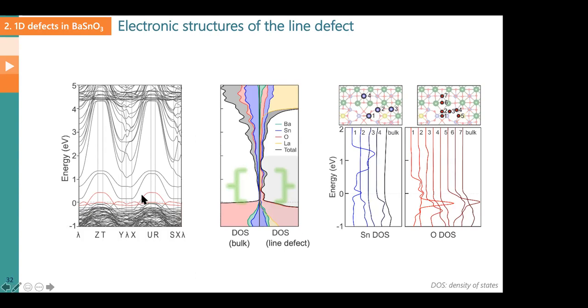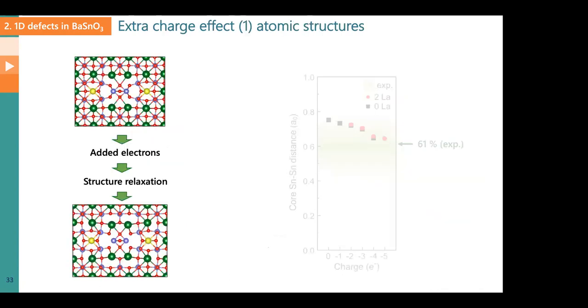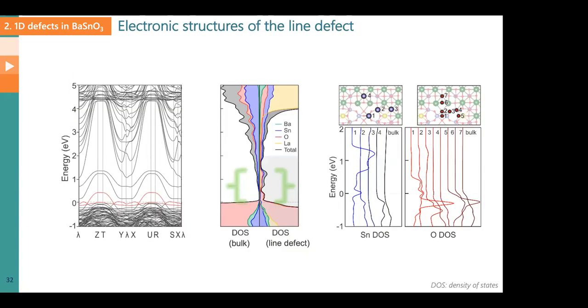But these red lines that come from a defect, from the barium and tin and oxygen, fill these prohibited energies. Now they're available there, allowing the defect to be metallic. So that's all good. We have a prediction that this defect should be metallic. We all got excited about it because now our defect has all of the hopes and promises to be metallic. We also have a good sense why: there are states between tin and oxygen bonds that create available energy levels in the structure so that electrons can easily zoom around.